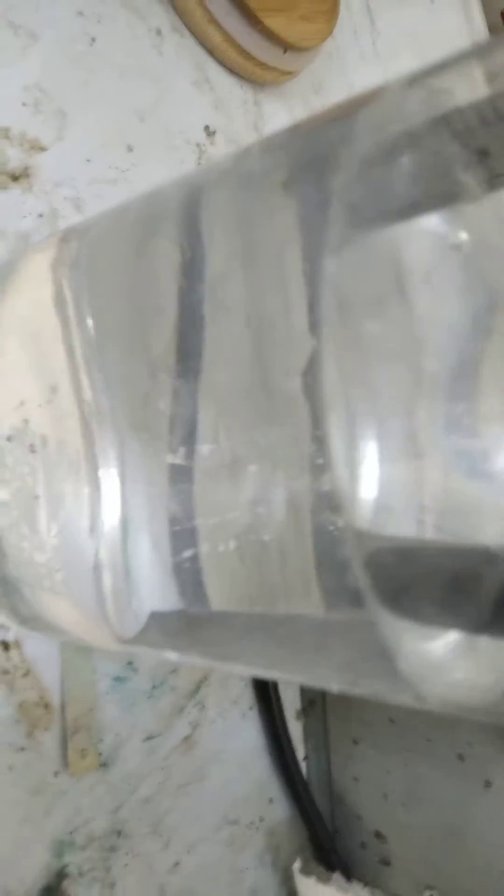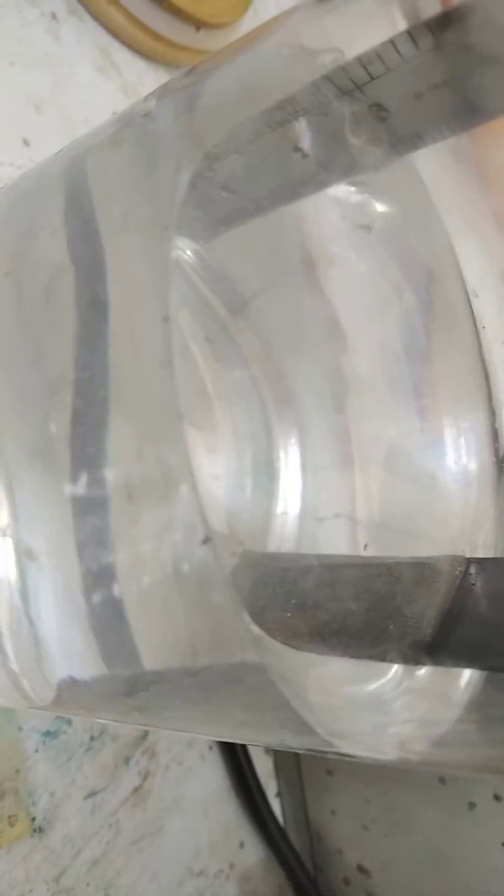This is our new lead dioxide on stainless steel and it seems to be working in an oxygen evolution environment. There's a solution of sodium perchlorate in water and it's being given an anodic polarization. So far there's no sign of any brown tinge that would otherwise be seen on an iron electrode, and of course the cathode is just ordinary stainless steel and from the top it looks pretty clean.